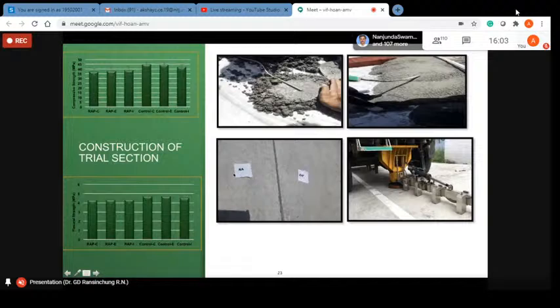And this is the falling weight deflectometer measuring the mechanical properties of the concrete for the different pavement sections, for natural aggregates and for the RAP materials. The mapping was done with one test at the corner, one at the edge, and one at the interior of the slab. Then the average value of the FWD was noted, and the FWD was conducted in accordance with IRC 117. Accordingly, the modulus of rupture and compressive strength were found. From this, we understood that 65% part replacement of natural coarse aggregate is very much doable.